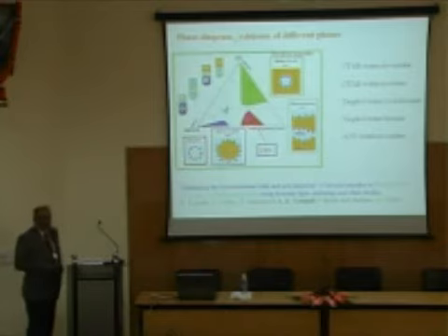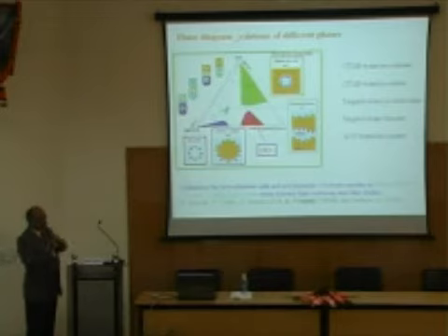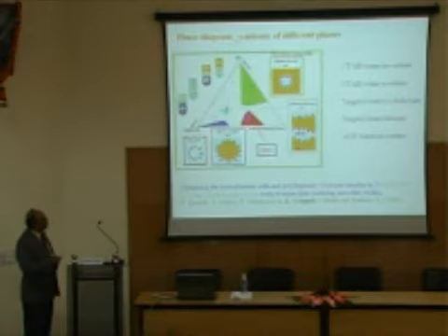Sometimes we have a fourth parameter which is called a co-surfactant, and you must know when you have to plot what is called a phase diagram. That means if I take X amount of this or Y amount of this or Z amount of this, what will I get? So, by knowing the phase diagram, you know what kind of structure you will get. Okay? So, you can get a micelle or a reverse micelle or a bicontinuous medium, etc. So these are all design. So these are some materials, nanoparticles we make. Okay, I missed that.